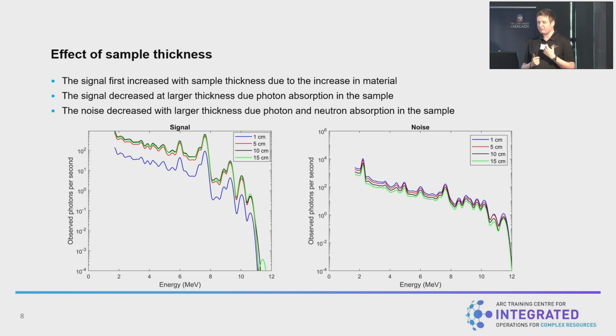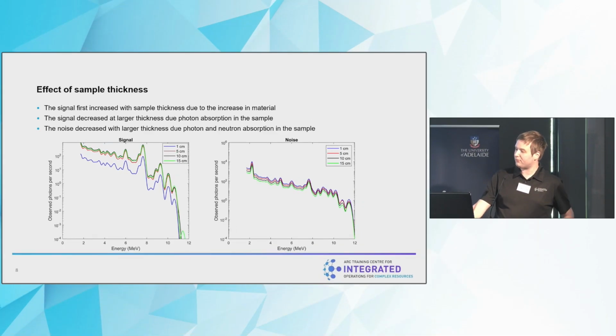Looking at the signal on the left, it's possible to see that with increasing sample thickness, the signal begins to increase up to 10 centimeters, after which there is a decrease. This increase is due to there being more material to be sampled, but also due to the reduction of the neutron energies by moderation, boosting the activation potential. But we can see at greater thicknesses, absorption of the signal photons does reduce the measured signal. However, if we look at the noise, we can see that there is a clear and consistent reduction of noise with increasing thickness, due to both neutrons and photons being absorbed within the sample, reducing that noise and helping boost the signal-to-noise ratio.